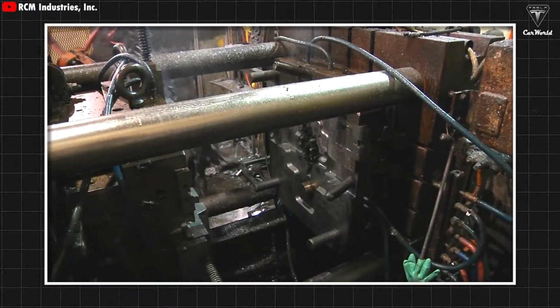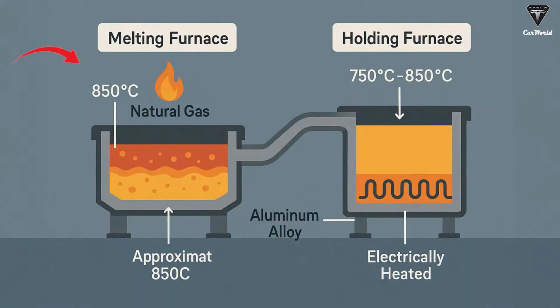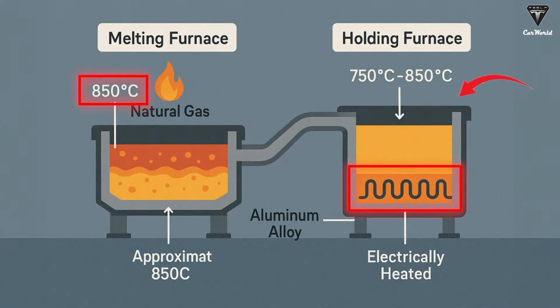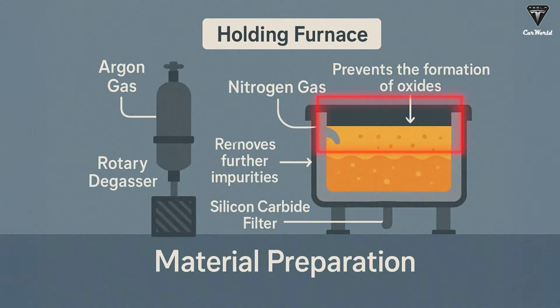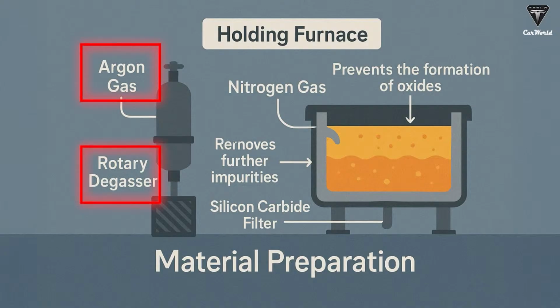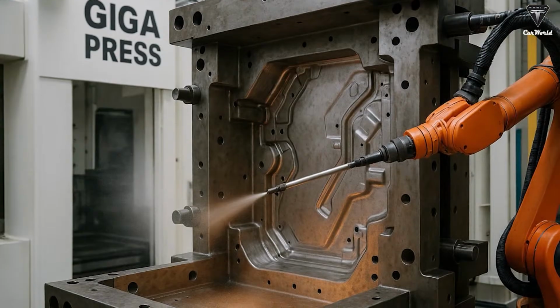From what we know, the Giga Press uses a 2-furnace system to process the aluminum alloy. One acts as a melting furnace, powered by natural gas and operating at around 850 degrees Celsius. The other stores the molten metal and is electrically heated, maintaining a temperature between 750 degrees Celsius and 850 degrees Celsius, as mentioned earlier. The empty space inside the holding furnace is filled with nitrogen gas, which helps prevent the formation of oxides in the molten aluminum. It also helps maintain a consistent temperature. Additionally, operators use argon gas, a rotary degasser, and a silicon carbide filter to remove further impurities and particles larger than 25 microns. That covers the material preparation stage.